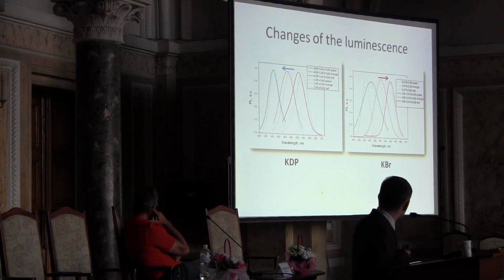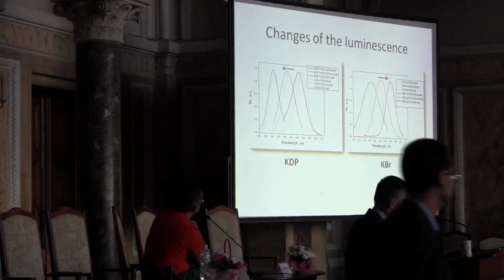In case of KDP, we always observe a blue shift, which is also size dependent. That is interesting: the smaller the particles, the smaller the shift here. But if you look at the potassium bromide, the smaller the particles, the larger the shift you observe, but also into the red.